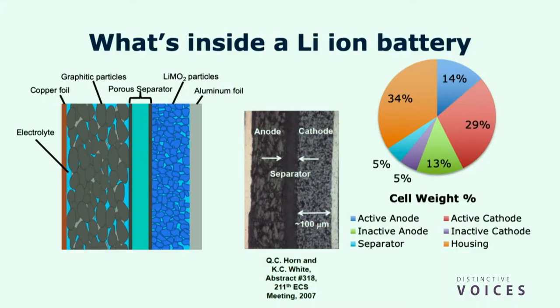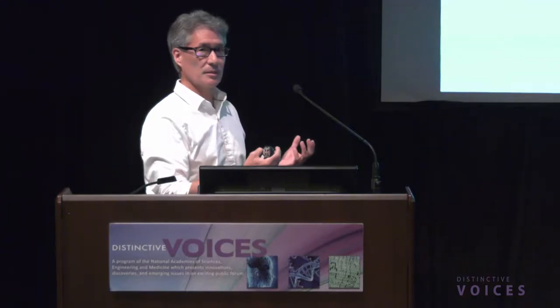So if one opens up a lithium-ion cell, you'll see that it consists of particles that are on the order of maybe a few tens of microns. The diameter of a human hair is about 50 to 60 microns, depending on who it is. These particles are maybe 5 to 10 microns, and there are many particles stuck together with a certain kind of binder, and they comprise the anode if it's graphite, and some lithium metal oxide if it's the cathode. And then in between, again, is this polymeric separator that's saturated with the liquid electrolyte. In other words, this light blue phase permeates from left to right. So everything inside a lithium-ion cell is wetted by the liquid electrolyte.